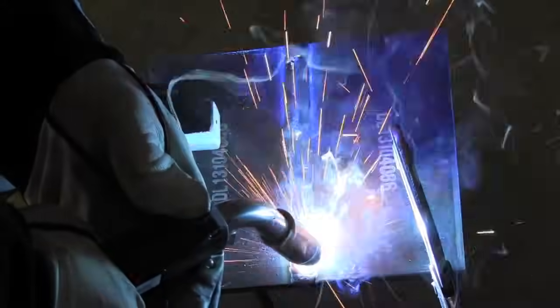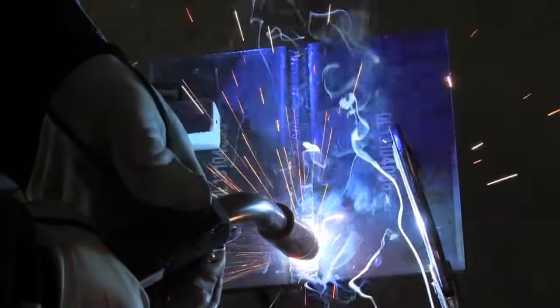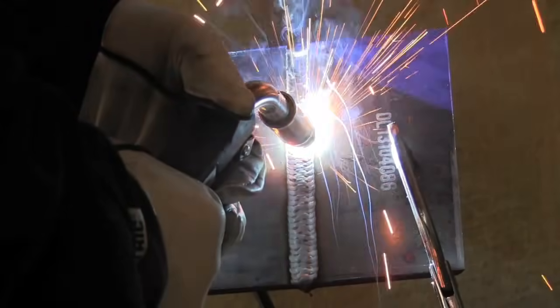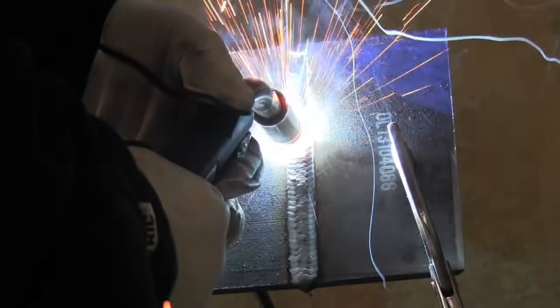Now this looks like I'm actually using a little bit of a drag angle, but I'm not. It's a little bit deceiving on the angle that I'm filming from. I'm trying to hold dead straight 90 degrees or a very slight push angle, but same technique here. I'm moving really quickly across the middle, pausing on the toes.